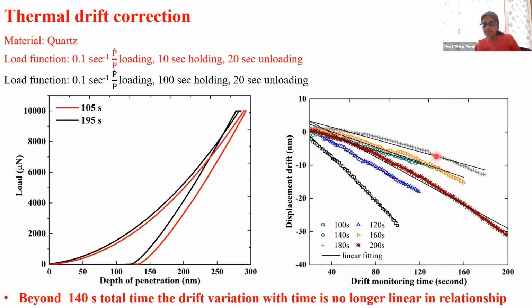But here you see these pluses are 180 seconds. And you see that the straight line fit is useless. Here is 160 seconds, here is 200 seconds. The straight line fit means nothing. So I need another scheme for drift correction. In a previous paper, we proposed a quadratic drift correction, which is not what I'm going to talk about this time. I'm going to propose a much simpler relation.